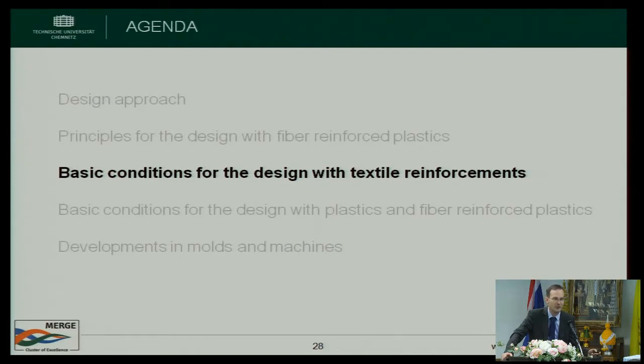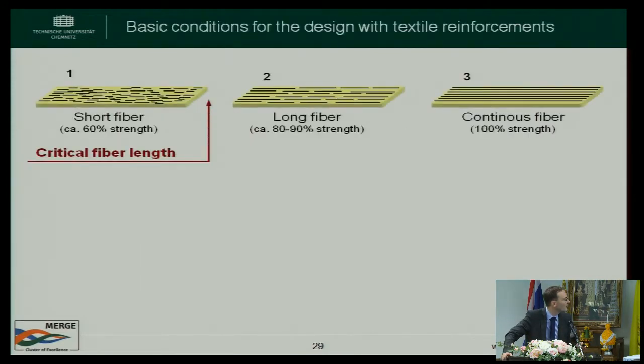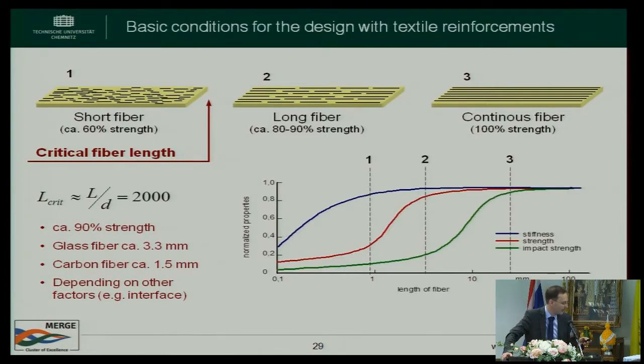So your boundary conditions for the part, especially for the reinforcement effect, depend on the design of your textile, because with the design of your textile fabric you can adapt your fiber volume content, your fiber orientation, the thickness of your laminate, and so on. But you always have to keep in mind that the reinforcement effect is only in fiber direction, not perpendicular to it. First you have to look at what loads you want to apply on your part,